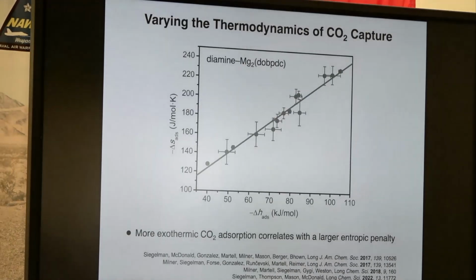And so if we think about the thermodynamics that's moving the step, this is 13 different diamines in the same magnesium MOF that I showed you. So each point here is a different diamine. And what I plotted along the horizontal axis is the enthalpy of the reaction with CO2, and the vertical axis is entropy. And what you can see is we can adjust the enthalpy of that reaction anywhere from minus 40 kilojoules per mole to out past minus 100 kilojoules per mole.